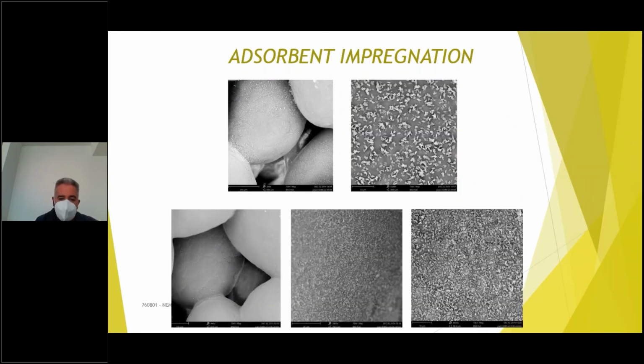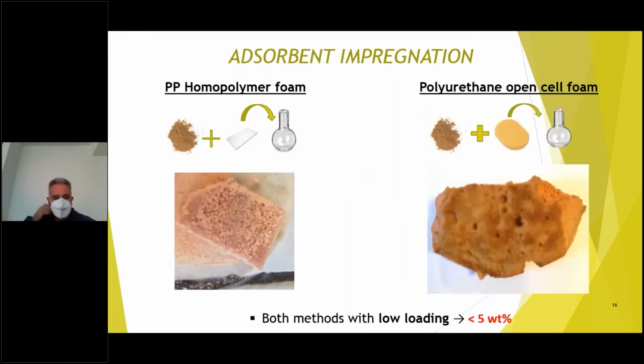We can make this impregnation process, and we have tried it with other geometries. For example, in this case, we have small ball foams, a typical foam based on polypropylene. You can see that you can reach a very high degree of impregnation on the surface. For example, in the bottom right photograph, we can see that the whole surface of these spherical particles that form the foam is completely impregnated and covered by the MOF crystals. Summarizing this adsorbent impregnation process, we have worked with polypropylene foams, and you can see the result, a macro photograph of this impregnation, and impregnation with polyurethane.